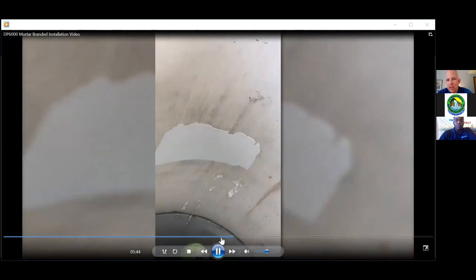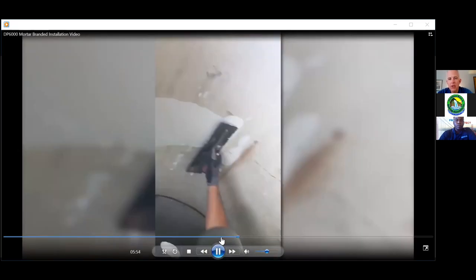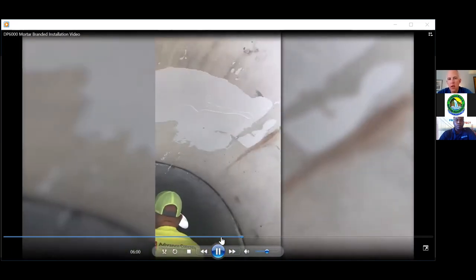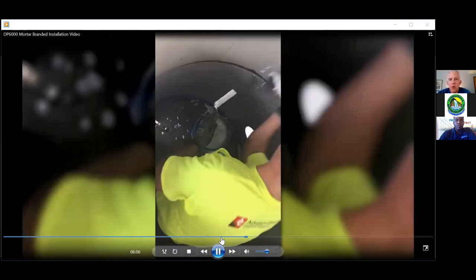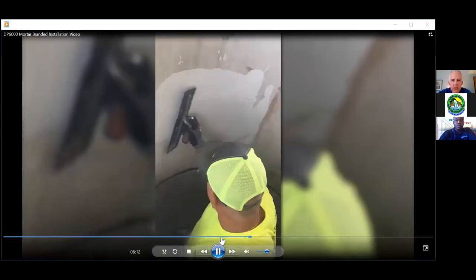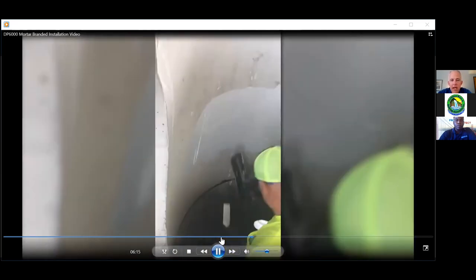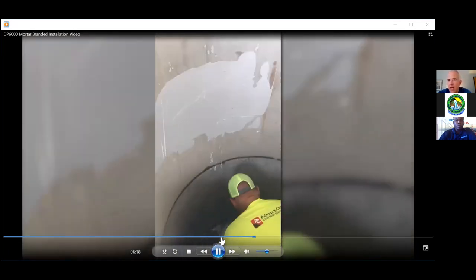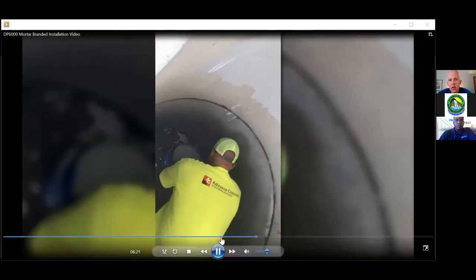This, on existing concrete, on concrete that needs rehabilitation, you can build this particular material up to about a half inch per application, and that way you can actually rehabilitate your concrete and put a protective liner on there all at once. On this test structure that we were doing in this video, this was just a new piece because he just wanted something there to where his guys could practice troweling it a little bit. But again, as you can see, he's putting about an eighth of an inch on in each different pass. So that is enough of a corrosion protection system to where, again, this is going to be a 30-year life cycle on this material, and we're not going to have any concrete degradation to speak of.